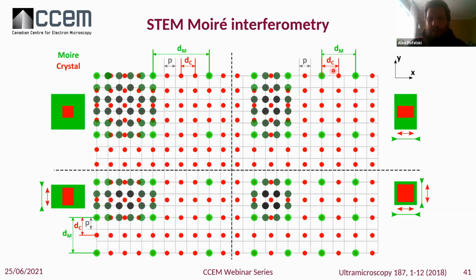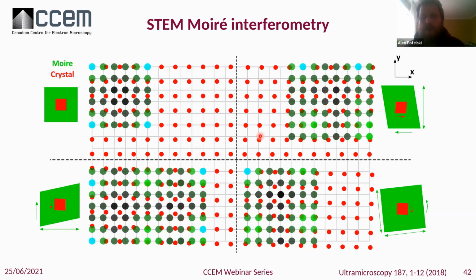If your crystal lattice has a certain strain, so you change, for example, the spacing here, you can see that this Moiré spacing is changing in a certain manner. In that case, this was made bigger, and the Moiré spacing becomes smaller. You can do the same in the vertical direction and have both combined. So there is here an intuition, this feeling that the Moiré signal is varying with the strain. But the geometrical link is not that obvious. It becomes even more complicated when you, for example, consider a shear.